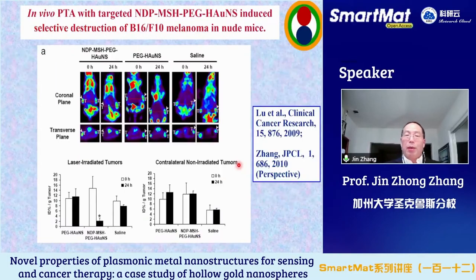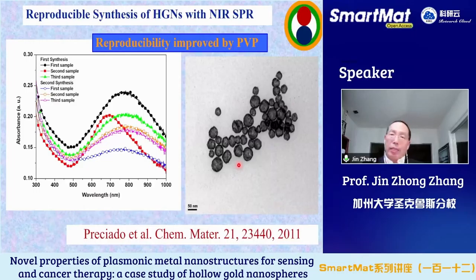Very successful. But we spent the last decade, 10 years, working on recipe strategy to make near-infrared absorbing, more reproducible HGNs. This is one of those efforts. We use a polymer to passivate the surface to make it more reproducible in synthesis. It does work. However, you see these HGNs are not very uniform in size.